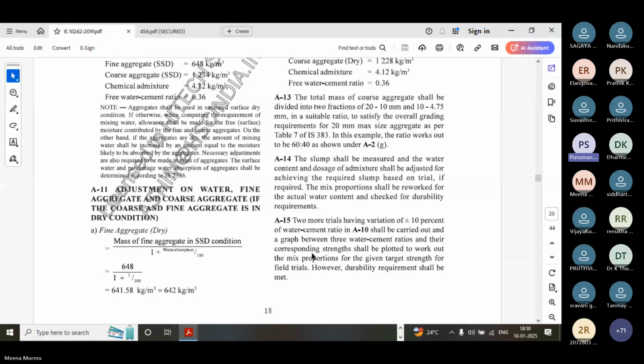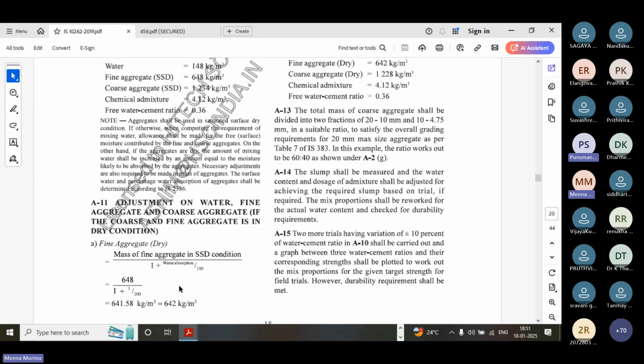And field people are using aggregate in dry condition. So for dry condition, what is the weight of aggregate we have to calculate? Mass of fine aggregate in SSD condition divided by 1 plus water absorption divided by 100. It was 648 as per the surface saturated dry, and as per the dry condition it is coming 642. So the quantity of the aggregate is reducing.